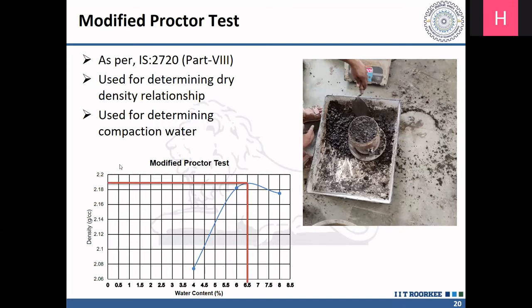From this exercise, we would be able to map the amount of water to be admixed to ensure the optimum moisture content, because this would ensure the workability of the mixture. The workability of the mixture is important for ensuring proper compaction, and proper compaction is important to achieve a good degree of compactness. If that is not achieved, then the air voids would be substantial, as a result of which the pavement structure might compromise in the durability aspect. These parameters are interrelated to each other, so we have to have good control on them.